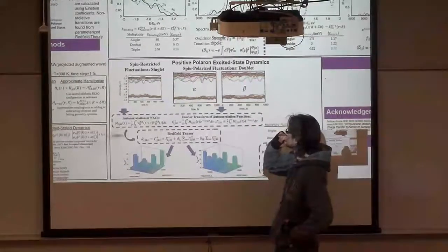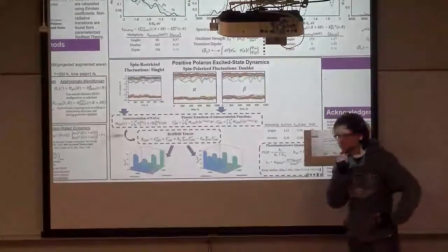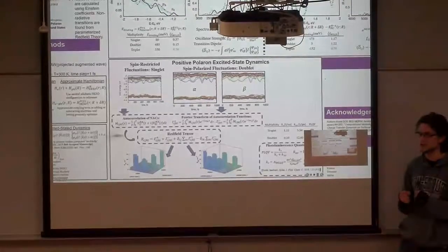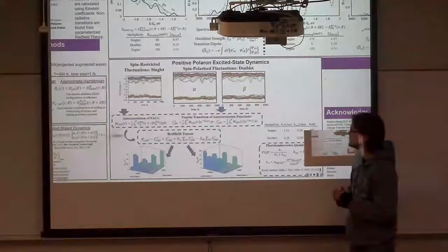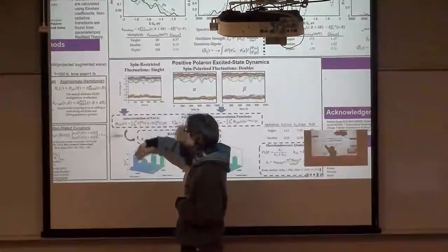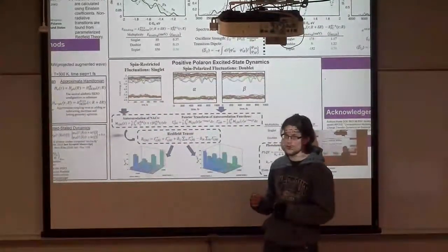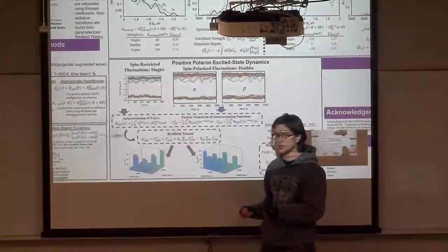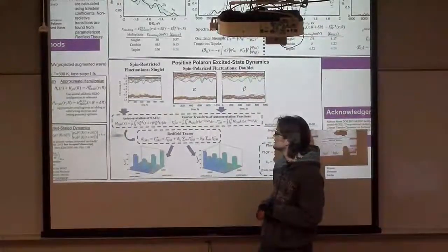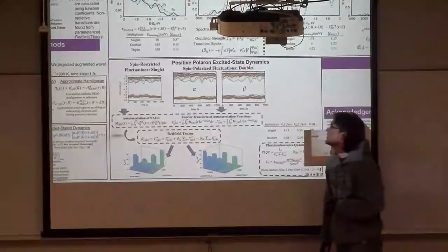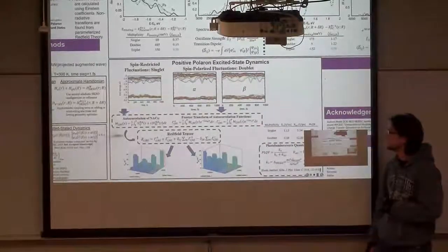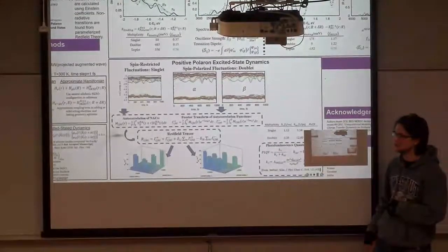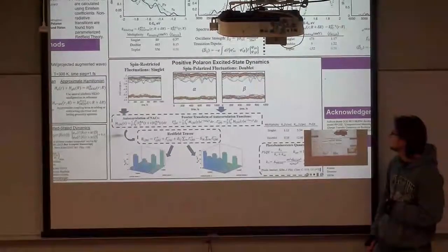To do our dynamics, we actually have to couple electronic and nuclear degrees of freedom. We do that using adiabatic molecular dynamics. These figures show the energy fluctuations of the Kohn-Sham orbitals along the trajectory. These fluctuations correspond to coupling to phonon modes along the trajectory. And if you've taken enough statistical mechanics, you probably have it burned into your mind that fluctuations lead to dissipation. So that's why we start with showing energy fluctuations of our models.